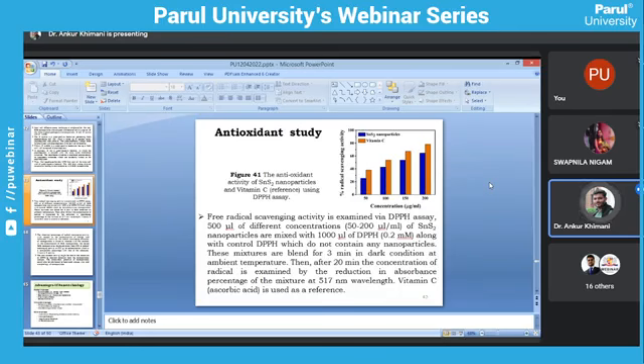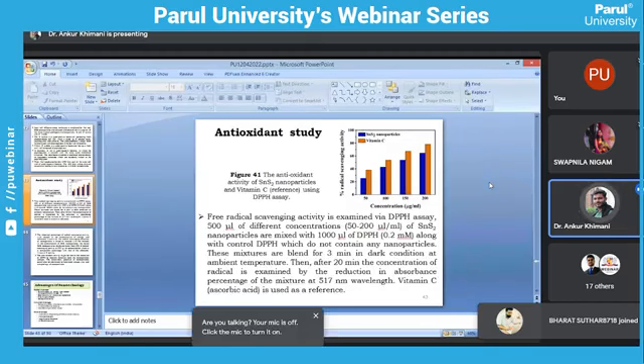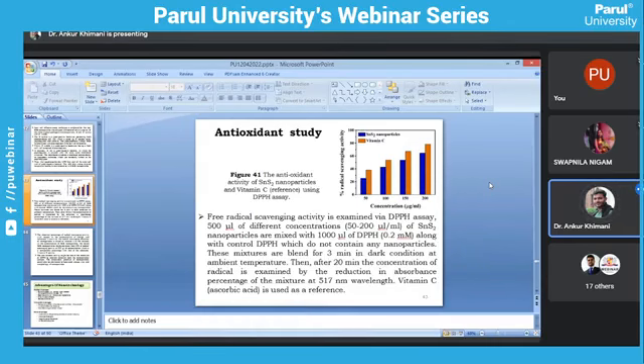500 microliter of the different concentrations, 50 to 200 microgram per ml of SnS2 nanoparticle, are mixed with 1000 microliter of DPPH, that is 0.2 millimolar, along with the control DPPH, which does not contain any nanoparticle. This mixture is blended for 3 minutes in dark condition at ambient temperature. Then after 20 minutes, the concentration of the radical is examined by the reduction in absorption percentage of the mixture at 517 nanometer wavelength. Vitamin C, that is ascorbic acid, is used as the reference.